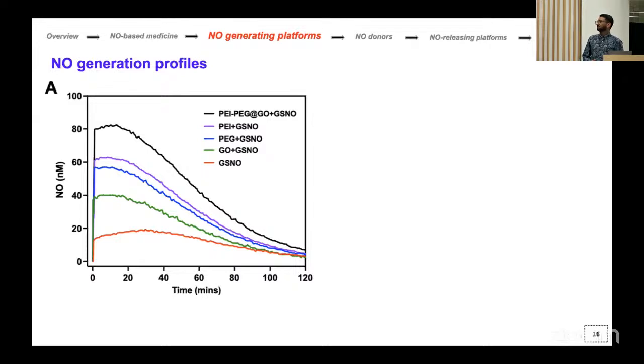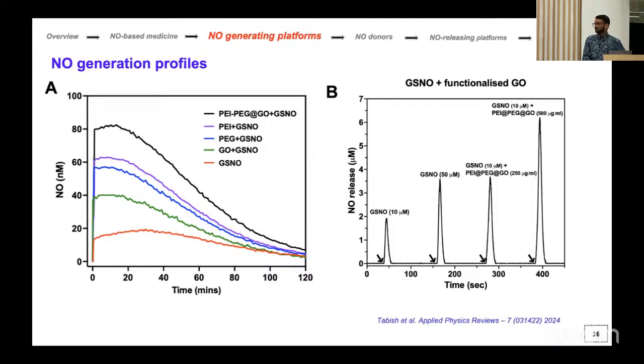But if we use it with unconjugated graphene and then with conjugated graphene, we see that we can release nitric oxide up to 8 micromolar out of 10 micromolar. So that's also therapeutically relevant. And then we show using ozone-based chemiluminescence how much nitric oxide we can produce, for example, first just from GSNO, 10 micromolar, and then using conjugated graphene. And we published this paper, Tabish et al., recently in Applied Physics Reviews.